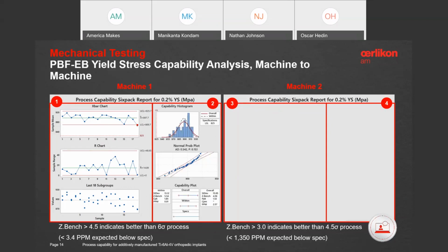Final check, we need to verify that our data set represents a normal distribution. There are many ways of doing this, but one way is to draw a normal probability plot, calculate the so-called probability value, and see if the p-value is greater than 5%. In that case, the data should essentially fit a straight diagonal line. As shown, the plotted data points seem to line up, and the p-value satisfies the conditions for normality. Consequently, the tensile data for machine number 1 can be considered normally distributed.